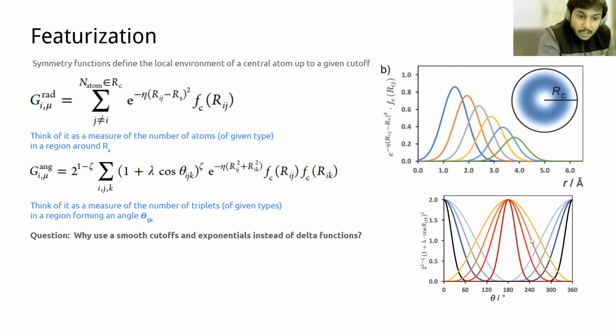What you do with these wider Gaussians is that you keep accumulating everything which is not really a straight line, but something rather flexible, which also includes up to, let's say, 60 degrees or something. And similarly, you could do the other way around where you probe angles on the other side, and you can develop these in a way that you are kind of uniformly sampling the angular space as well as the radial space around the atom. Those are the two aspects.